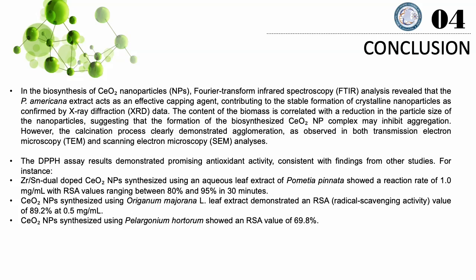In the biosynthesis of cerium oxide nanoparticles, FTIR analysis revealed that Persea americana extract acts as an effective capping agent, contributing to the stable formation of crystalline nanoparticles as confirmed by XRD data. The content of the biomass is correlated with the reduction in the particle size of nanoparticles, suggesting that the formation of the biosynthesized cerium oxide nanoparticle complex may inhibit aggregation. However, the calcination process clearly demonstrated agglomeration, as observed in both transmission electron microscopy and scanning electron microscopy analysis.